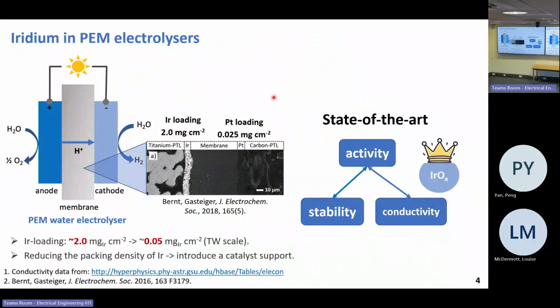The main factor that hinders the mass implementation of PEM electrolysers is that it uses precious metals like iridium and platinum as catalyst. Iridium and platinum, precious metals as catalyst. You actually need platinum? Yes, we need iridium and platinum as the catalyst for hydrogen evolution and oxygen evolution reactions. Yeah, they are very expensive.